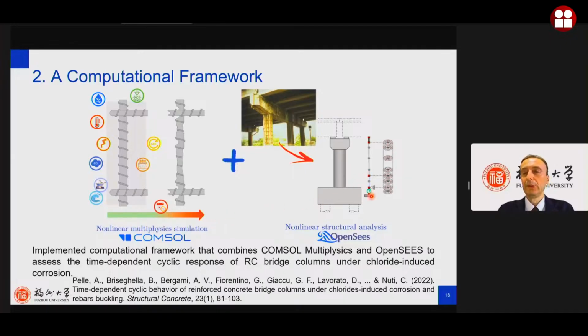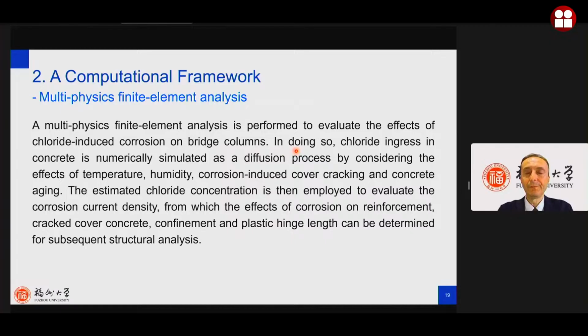And after, to do the structural simulation using a finite element software. In this case, we use OpenSees, but also other software, SAP2000 or whatever you want, can be used. In the COMSOL software, the chloride ingress in concrete was simulated as a diffusion process, and we consider the effect of temperature, humidity, corrosion-induced cover cracking, and concrete aging.